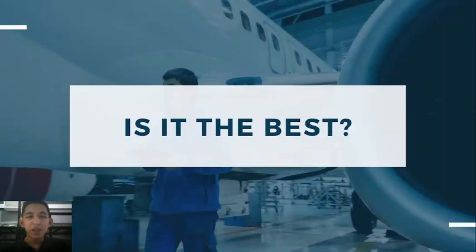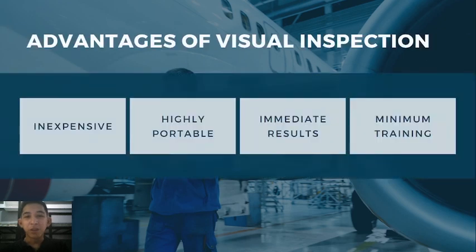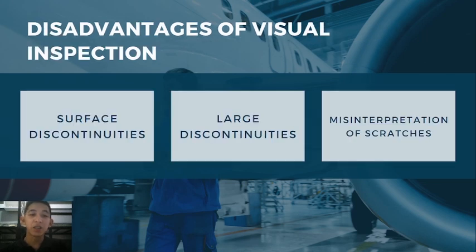Does that mean it is the best NDI method there is? Not quite. There are different NDIs that have advantages and disadvantages. For visual inspection, it is inexpensive and highly portable. You can have immediate results and it requires minimum training and minimum part preparation. However, because it is visual, we can only detect surface discontinuities. Generally, only large discontinuities are detected and misinterpretation of scratches may occur.